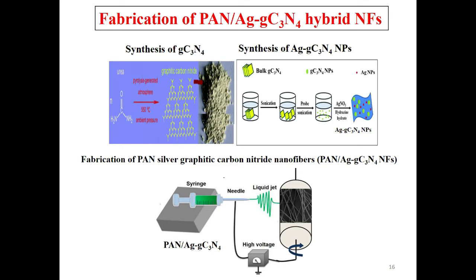A particular bulk amount of graphitic carbon nitride is dissolved into the solution and then sonicated for uniform dispersion of the graphitic carbon nitride into the solution. That graphitic carbon nitride nanoparticle then proceeds to in situ deposition of silver nanoparticle synthesis, and that in situ process gives the silver graphitic carbon nitride nanoparticles. This particular nanoparticle is then dissolved in dimethyl formamide.